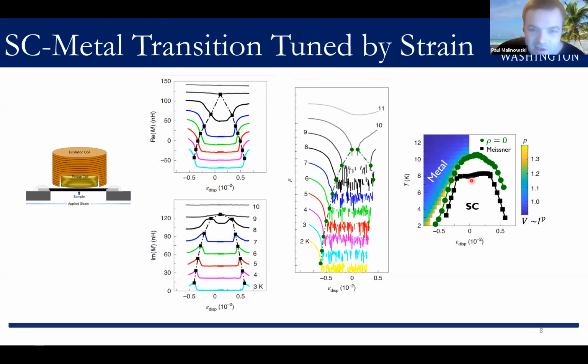Yeah, that's a great question. I'm not sure. I know that previous work has shown that the critical currents or the pinning of the vortices depends a lot on the domains. So when you detwin the crystal, you can get changes in the critical currents, for instance. And I think that might help explain this, because you see that the thermodynamic measurement is quite flat, whereas the TC measured by resistivity is changing a little bit here. I haven't thought too much about what you just said, but I think that's a very interesting idea. Definitely in terms of measuring TC by resistivity, the domains can have an effect. I'm not so sure about the thermodynamic measurement. I think that should be independent of domains.